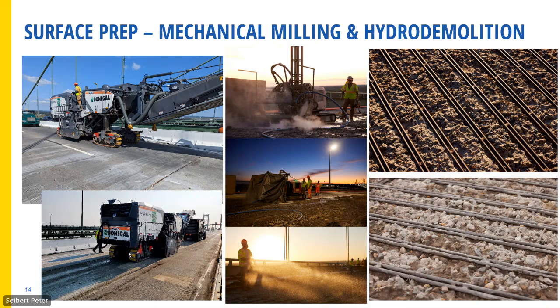Followed up by hydrodemolition process. You can see some of those photos down the middle. And on the right there, the rebar is exposed. Although it wasn't technically supposed to be exposed when you go down 2 inches, the rebar is just lower than 2 inches. You can see the deck between is a little higher, but that paste, there's no aggregate to hold it. That paste around the bars winds up coming off during the hydrodemolition process, which exposed a lot of that rebar. And it was kind of a good thing because we saw some corroded bars we were able to repair and put some replacement bars in along the way.